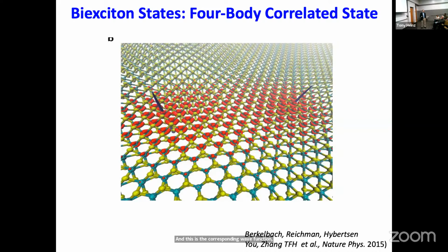Of course, the biexciton is sort of like the hydrogen molecule, but it's a little bit different in the sense that you can't use a Born-Oppenheimer approximation, right? So all 4 of the charges are light. And consequently, when you plot this thing, you have to sort of make projections into lower dimensional space. And these spikes would represent likely positions of the hole, and then this would be the electronic charge distribution. And this actually looks very much like a bonding molecular orbital, right? You get enhanced charge density in this region, and that kind of holds the two positive charges together. It's also interesting in the context of quantum information science, because this would be a building block for a solid state source that produces correlated pairs of photons.